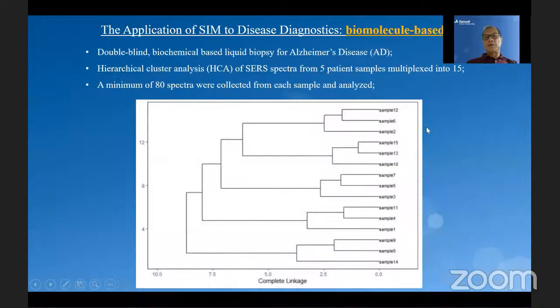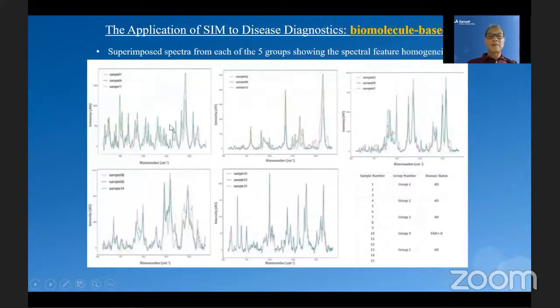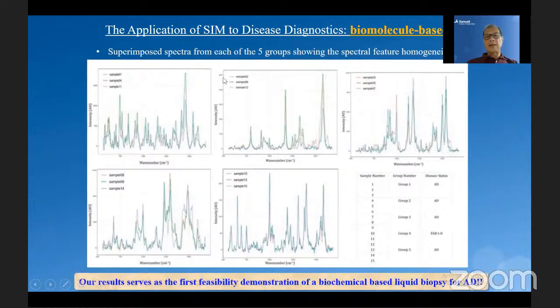We then performed a double-blind test using 5 patient samples multiplied into 15 samples, and we clustered them into these 5 groups. After the unblinding, we found a 100% match of these groups. This slide shows a superimposed spectral feature within each of the groups. And you can see the similarity within each group and the dissimilarity, or differences, between groups. So this serves as the first feasibility demonstration of a biochemical-based liquid biopsy for Alzheimer's disease.